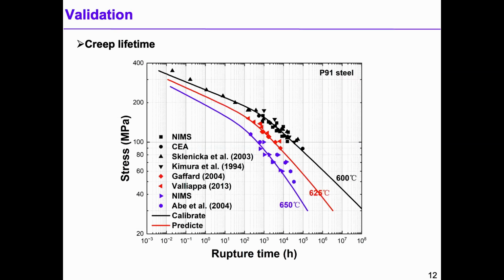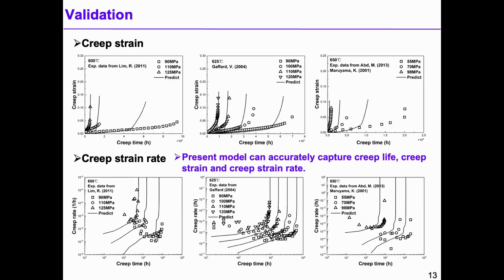This is our modeling results. From this picture, we can see our model can accurately capture the creep rupture time at high stress and temperature range. And this is another type of validation. We can see our model works well in predicting creep strain and creep strain rate. Above all, we can draw a conclusion. Our model can accurately capture the creep life, creep strain, and the creep strain rate. So we can use this model to conduct some similar work.